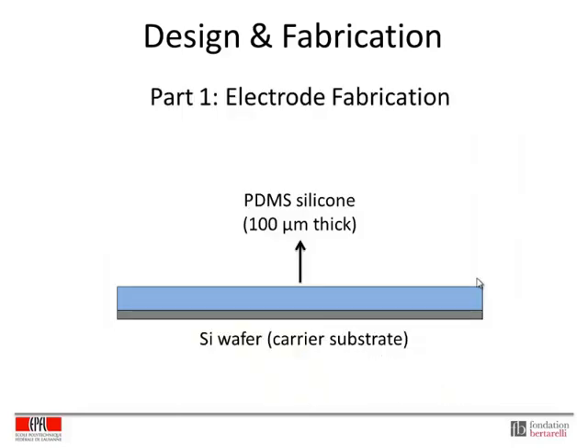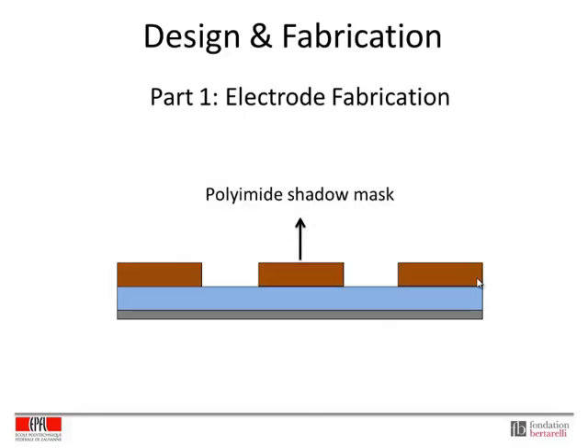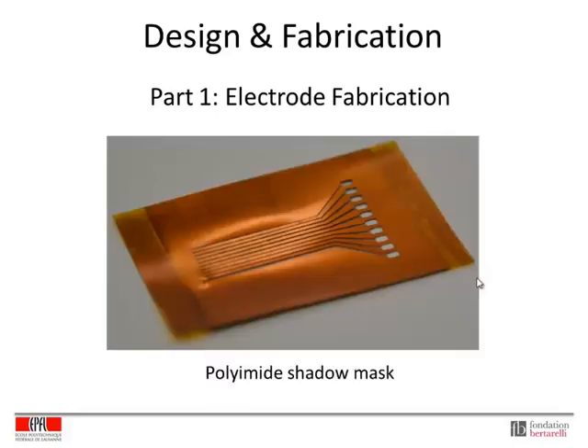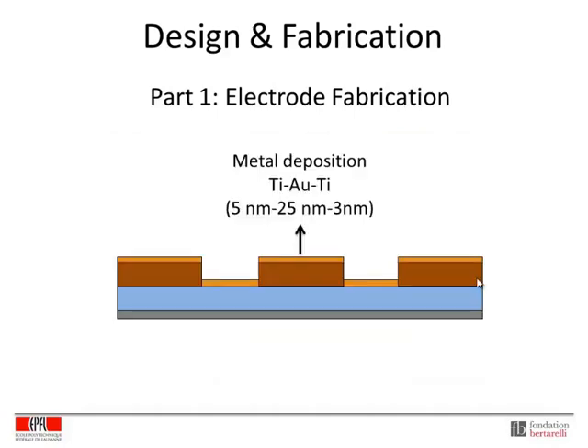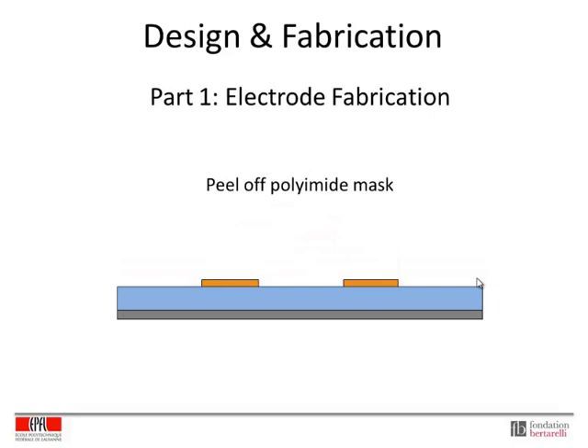So first we use silicon as our carrier substrate. We spin about 100 microns of PDMS. After curing, we take a polyimide shadow mask, and this is actually what we use to define the geometry of our electrode. So this is the top view image of the polyimide shadow mask, and the features on the right side are the pads, and they're about 1 millimeter squared. After this, we deposit metal, approximately 25 nanometers of gold sandwiched in between a few nanometers of titanium on each side for a better adhesion. After this, we peel off the polyimide mask, and we have our electrodes remaining. And then we just set this to the side for our second part.